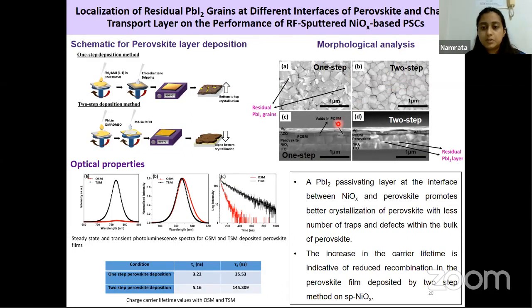And when we look at the cross section of the complete devices, we see that as in the previous study, we saw the voids due to the residual PbI2. We don't see any such voids here; we see a smooth interface. But we see some white spots like the one in figure A. We see white spots at the bottom interface, that is in between the nickel oxide and the perovskite layer. So when we perform the XRD for these white spots, we find the characteristic PbI2 peaks, and hence we assign the white grains to the residual PbI2.